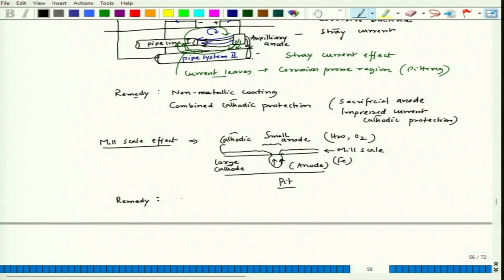So, that is where the advisable remedy could be, we can use shot blasting to remove mill scale completely. That way we can avoid such localized corrosion points due to the cathodic effect of the mill scale and the anodic effect of that small exposed area due to the break in the mill scale.